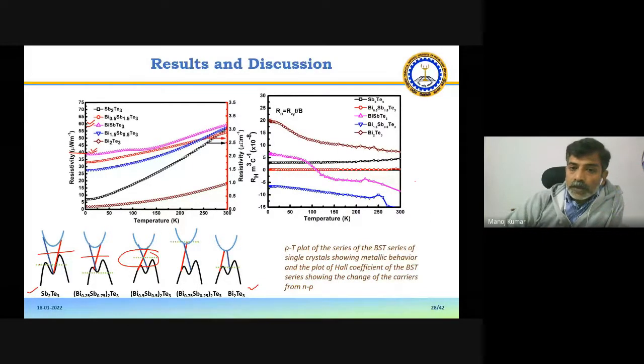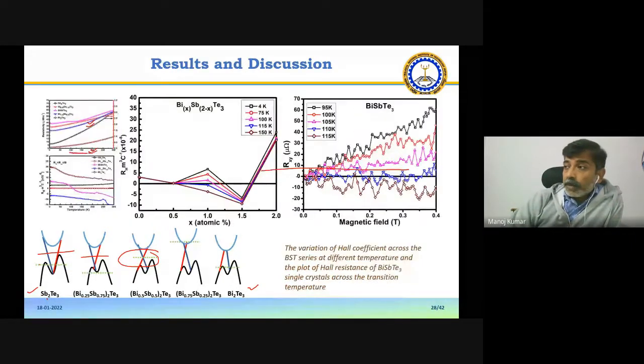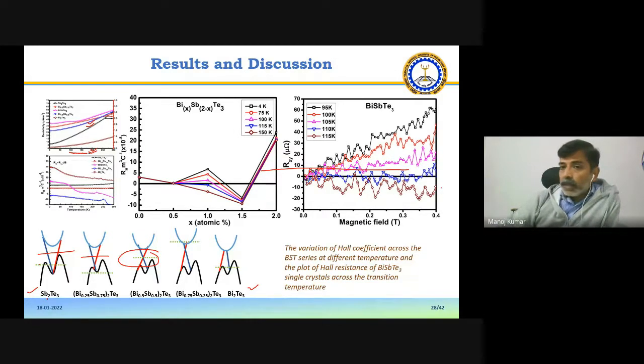And this was also confirmed: we actually tune the Fermi level from p-type to n-type while going from Sb2Te3 to Bi2Te3. Okay, so this was a confirmatory test. By measuring the Hall coefficient, we can confirm where our Fermi level is. If it is close to zero, it means both n-type and p-type carriers are in equal portions, and if it is positive, p-type carriers dominate. If it is negative, n-type carriers dominate. Based upon that input, we can locate its position in between the gap.